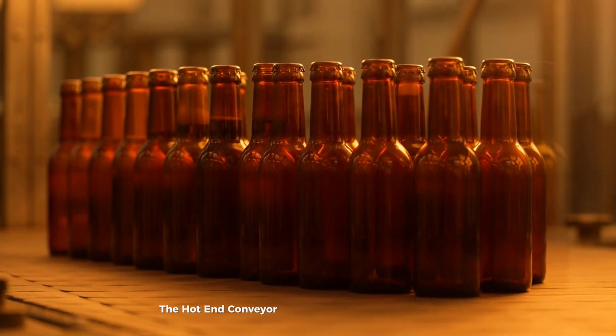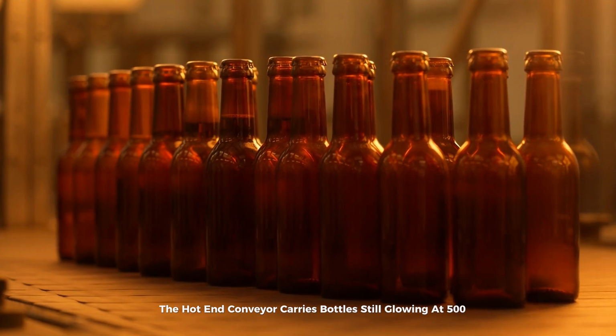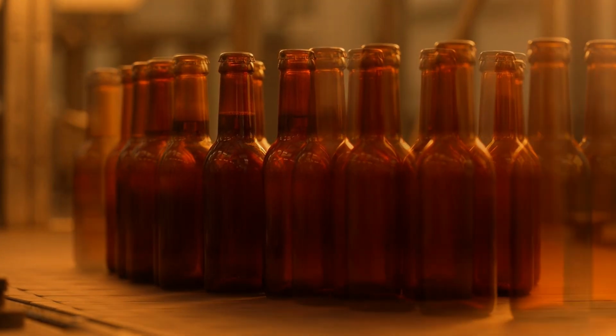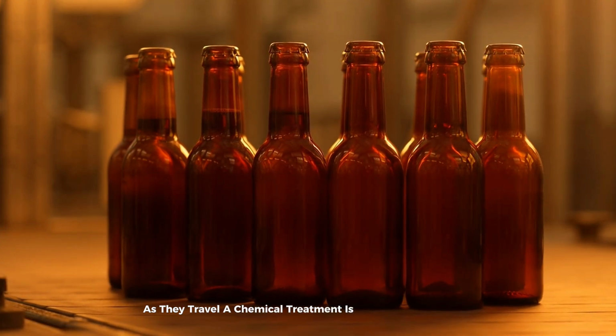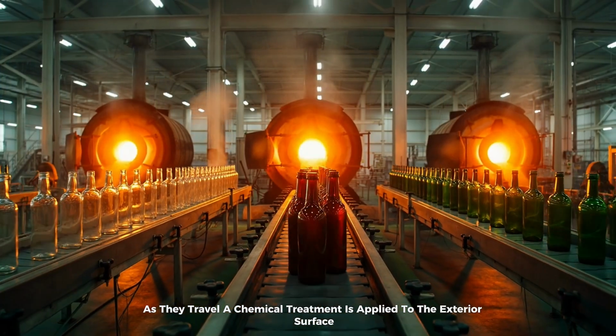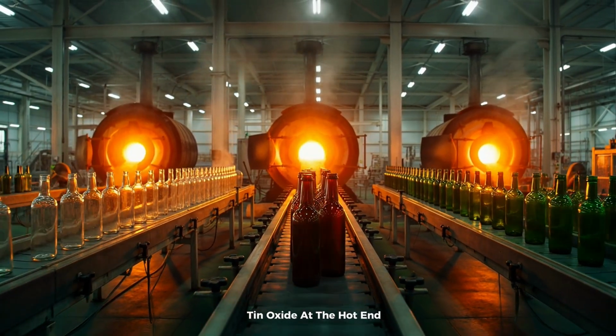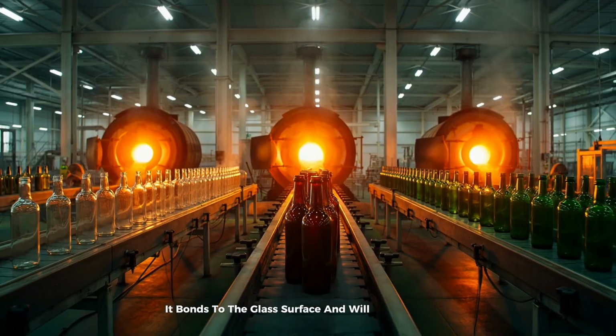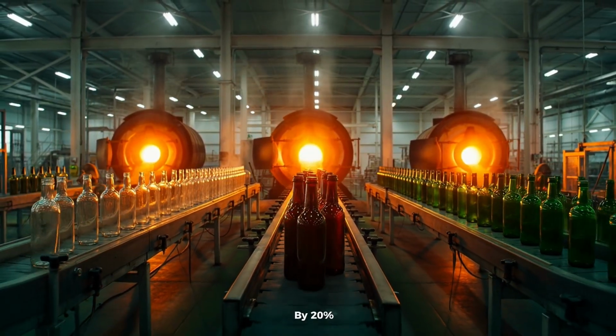The hot end conveyor carries bottles still glowing at 500 degrees toward the lehr entrance. As they travel, a chemical treatment is applied to the exterior surface. Tin oxide at the hot end. It bonds to the glass surface and will increase scratch resistance by 20%.